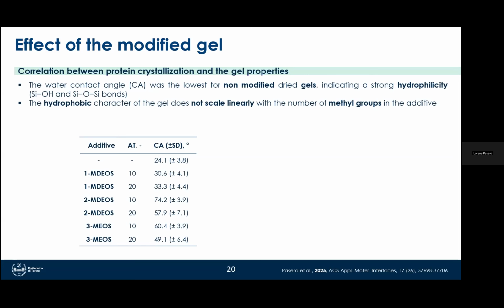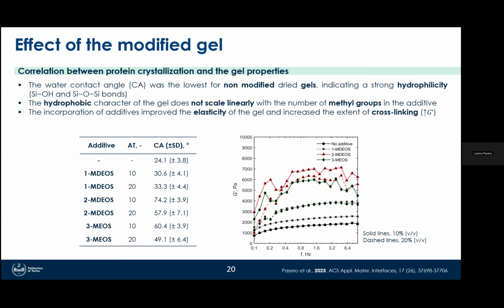So to explain this, we also assessed, let's say, the elasticity and the rheological properties of the gel. We looked at the mechanical properties and we saw that the additives increased the elasticity and the cross-linking by increasing the storage modulus. The lowest storage modulus was observed for the non-modified gel. And this incorporation of additives could improve the elasticity and the extent of cross-linking. And we hypothesized that in the presence of TMOS alone, the resulting gel was less interconnected due to the scarce accessibility of residual silanol groups, which are involved in the condensation reaction for the formation of the gel.